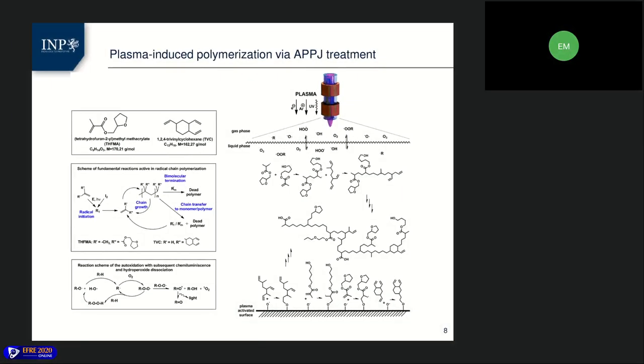The obtained results on the analysis of chemical composition of the studied films show that the plasma jet polymerization process substantially followed a conventional free radical chain polymerization pathway via vinyl or vinylidene bonds. An increased content of oxygen in the near surface region of films can be caused by post-oxidation processes, reaction with the activated air molecules due to the radical nature of the plasma polymerization. So here is the reaction scheme of the auto-oxidation process.